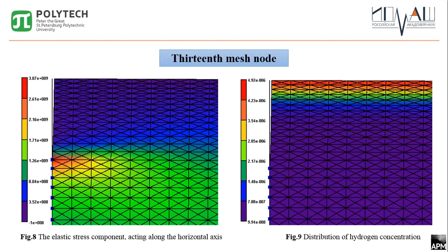0.102 ppm here. After that, the value of elastic stresses acting near the concentrator became so great that the background concentration existing in the material was sufficient to achieve the necessary reduction in the level of cohesive stresses. Consequently, fulfillment of the fracture criterion in each subsequent mesh node occurred instantly at the very first step in time integration.